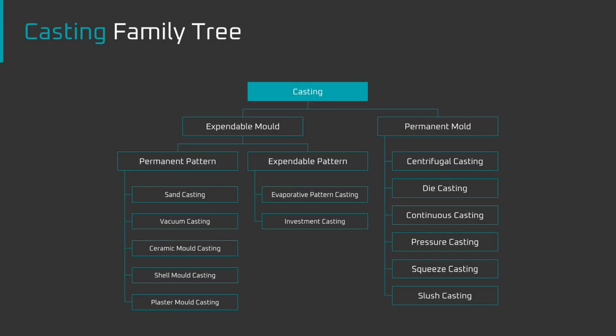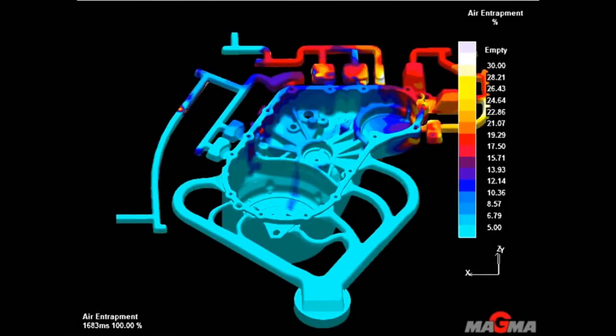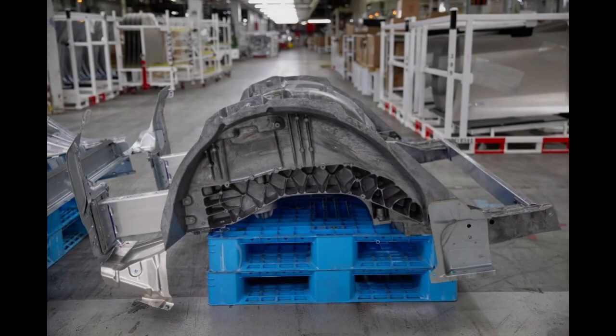Let's dive right into the challenges of Gigacasting and how they're solved. Depending on how you slice it, there are at least a dozen ways to cast molten aluminum. Tesla's Gigapresses use high pressure die-casting. High pressure die-casting can fill the die cavity in a tenth of a second, which allows for faster production rates. Additionally, due to the high injection velocity, it can produce intricate shapes because the molten aluminum can be injected before the metal has had a chance to cool. However, it does come with drawbacks — or if you think like an engineer, fun challenges.